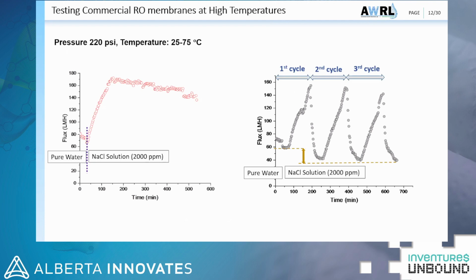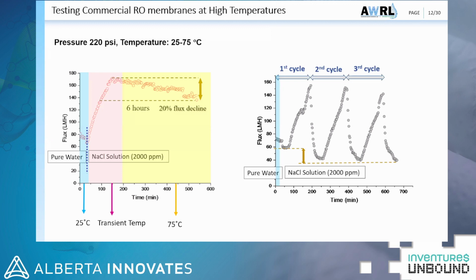Again, you can see here that by the continuous operation at 75 degrees C, the flux reduced gradually over time. The cyclic test of increasing and decreasing the temperature also showed flux decline over time at higher temperature.